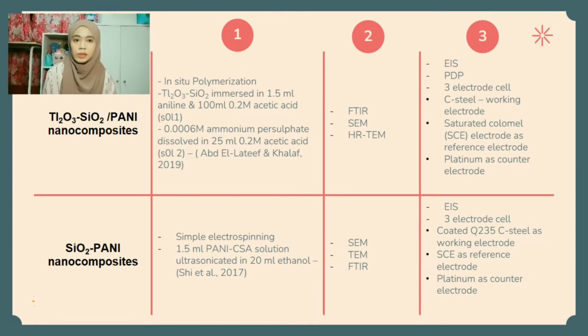In situ polymerization was used to synthesize thallium trioxide silica polyaniline nanocomposite. In a study conducted by Abd El-Lateef and Khalaf of 2019, the produced thallium trioxide silica nanocomposite were immersed in 1.5 ml of dispersed aniline solution and 100 ml of 0.2 molar acetic acid, which was labeled as solution 1. The mixture was then cooled in an ice bath at 4 degrees Celsius.